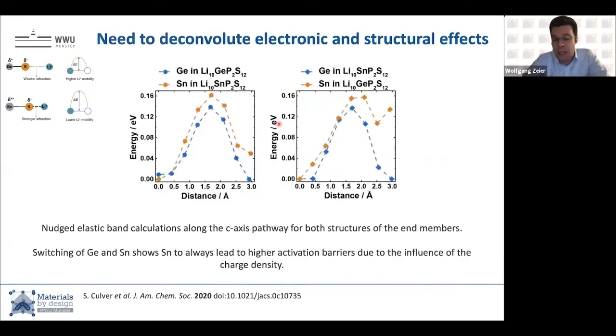Does it really affect the potential energy landscape? Well, one needs to deconvolute electronic and structural effects here, because clearly the structure is also changing. And so what we did was we looked at nudged elastic band calculations of pathway potential landscapes of lithium in the germanium phase and in the tin phase. And here, tin has the higher activation barrier. This is what we see in ionic transport in the measurements as well.